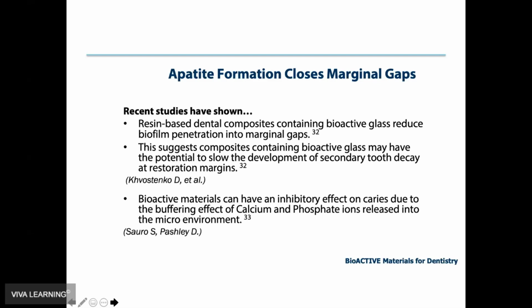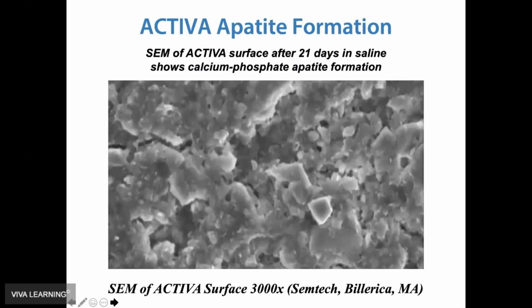released into the microenvironment. This buffering effect is big because there are patients that don't know which end of the toothbrush has the bristles. And bacterial metabolism produces an acidic byproduct that demineralizes tooth structure. So buffering ions can help decrease the negative, deleterious effects of these acids on tooth structure. Here's a slide that shows apatite formation on the surface of Activa Bioactive Restorative after 21 days in a saline solution, mimicking saliva, showing calcium phosphate apatite formation on the surface of the material.